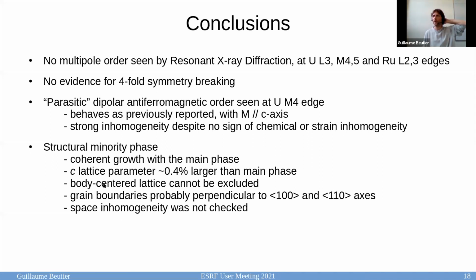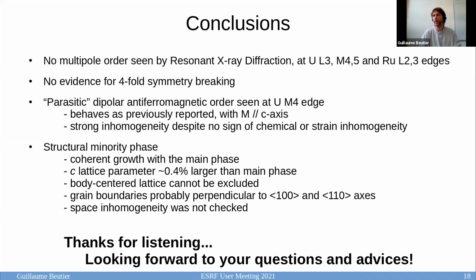Something that I haven't commented on is that this phase is probably also body-centered because we don't see any peaks close to the H plus K plus L odd superlattice reflections. And we see grain boundaries along the 100 and 110 axes. We could not check the spatial inhomogeneity. And so with that, I thank you for listening, and I'm looking forward to your questions and advice. Thank you very much.